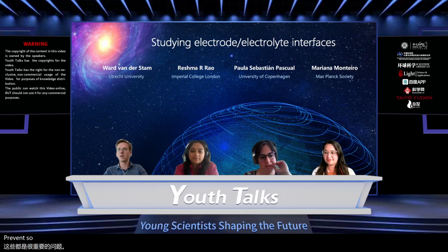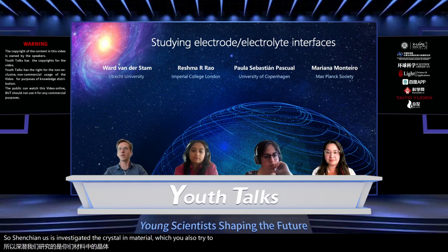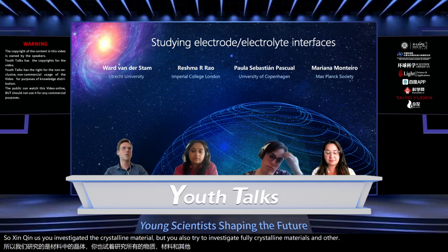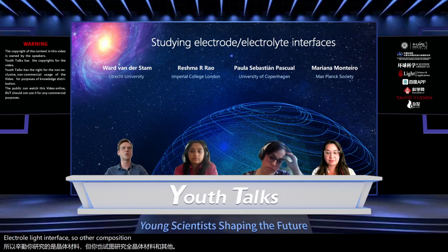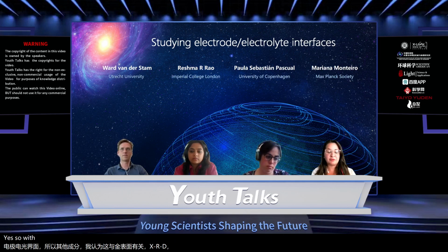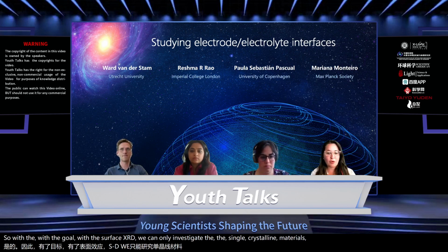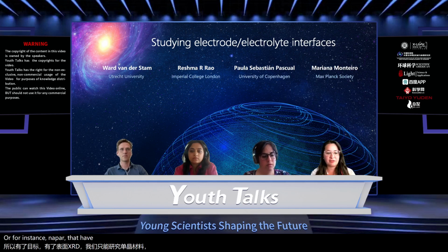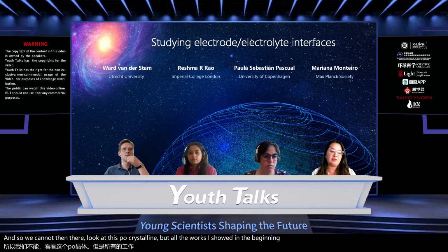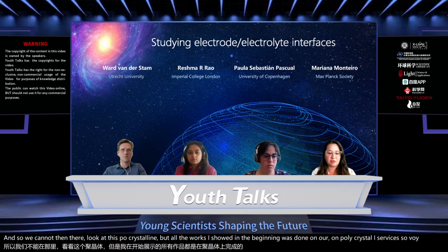Great. So there's a question from the audience for Mariana. Shin asks, you investigated the crystalline material, but did you also try to investigate polycrystalline materials and other electrolyte interfaces, so other compositions? I think this is related to the gold surface XRD. With surface XRD, we can only investigate single crystalline materials, or, for instance, nanoparticles that have very well defined single crystalline facets. So we cannot look at polycrystalline surfaces there, but all the work I showed in the beginning was done on polycrystalline surfaces, so polycrystalline gold and polycrystalline platinum.